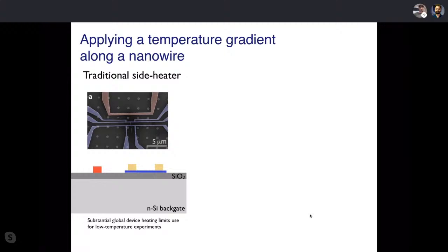Now, people have looked quite a bit at nanowires in thermoelectrics for quite some time. And here is a device that people typically use. So you can faintly see a nanowire here. If you can see it, I can see it. Then you have a 4-point contact system at either end of the nanowire. So these are your electric probes to measure thermal voltage, for example. Everything sits on a surface. Here you have a cross-section of that part. And then you put a heater system somewhere nearby so that you can heat from one side.